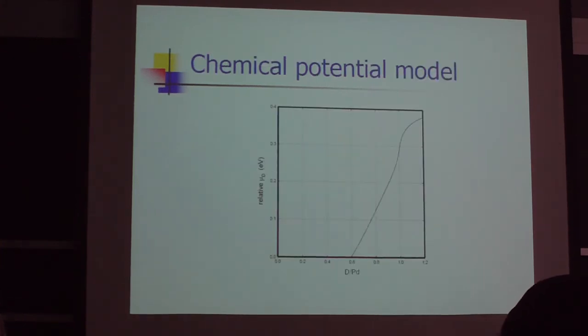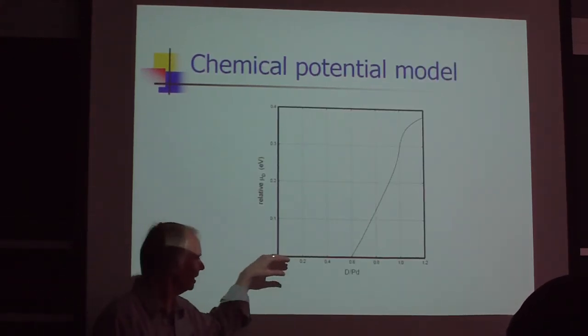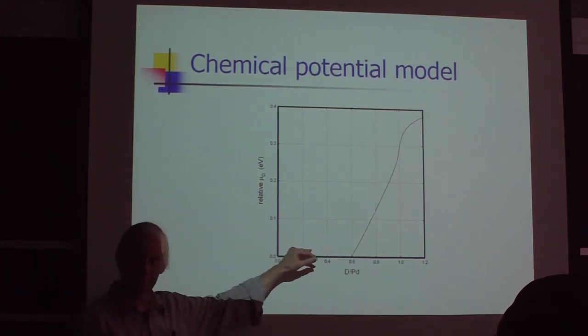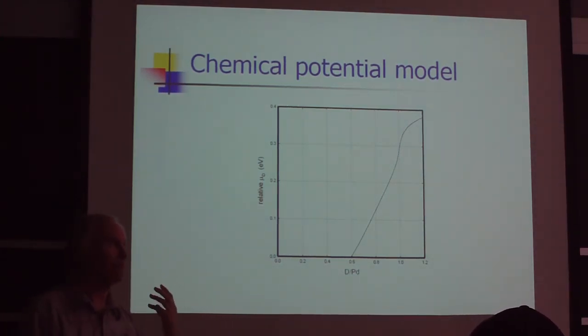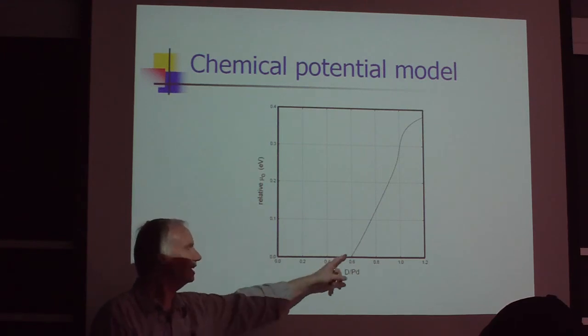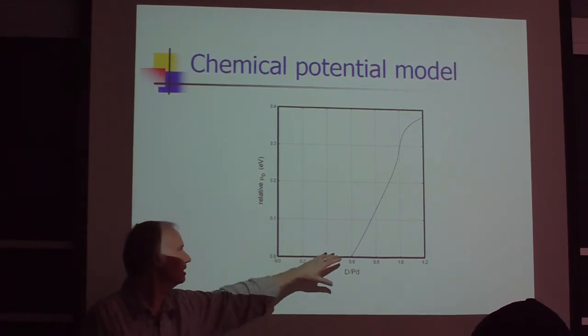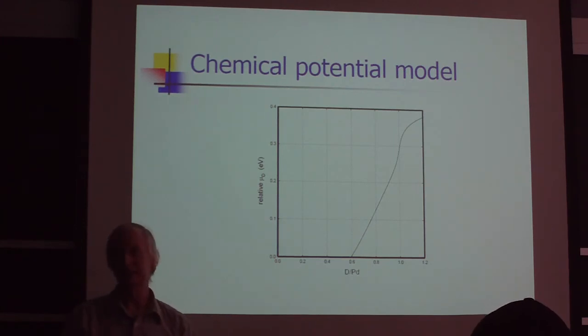And these are not the same, specifically for hydrogen diffusion in palladium. The reason is that the chemical potential in the miscibility gap is flat. It's flat because it's a two-phase region. For example, if you've got water and ice together, the temperature is near 32°F. If you raise the temperature, ice melts. Lower it, and water freezes. This is that kind of effect.